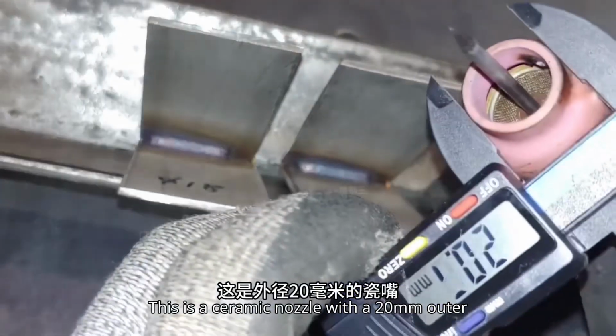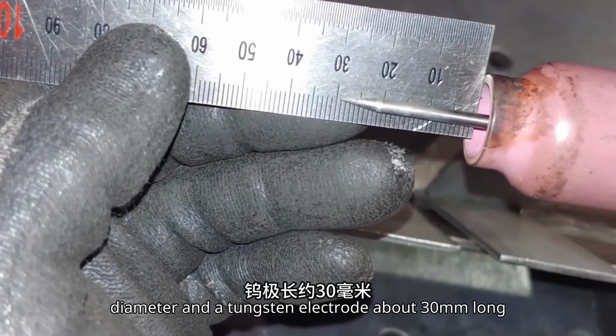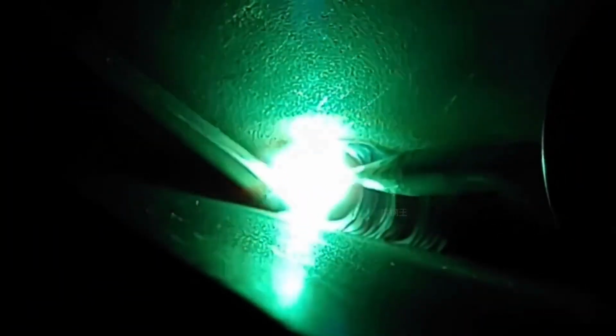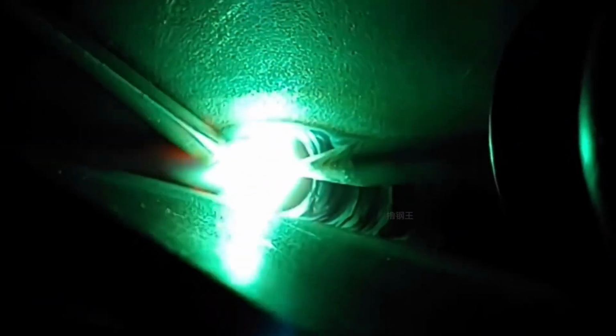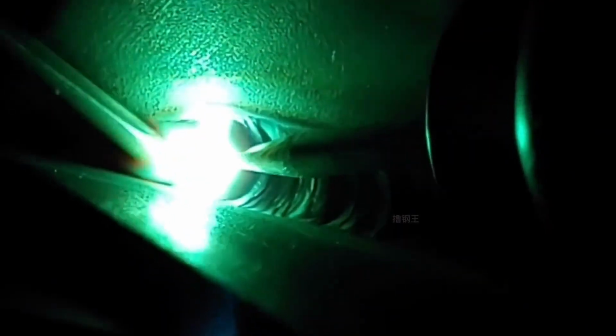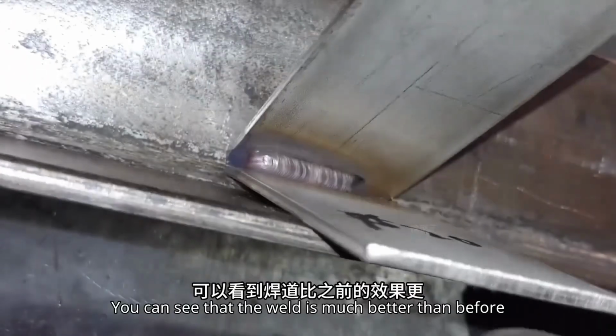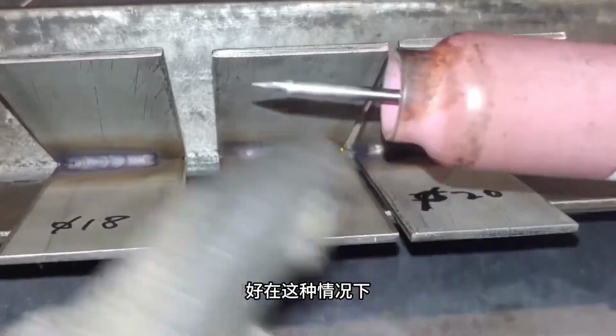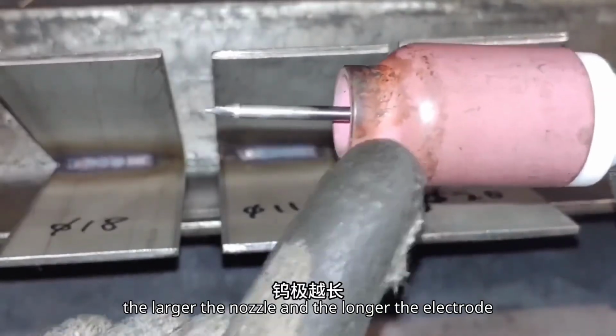This is a ceramic nozzle with a 20 mm outer diameter and a tungsten electrode about 30 mm long. The welder settings are the same as before. This is what we get after welding. You can see that the weld is much better than before. In this case, the larger the nozzle and the longer the electrode, the better the result.